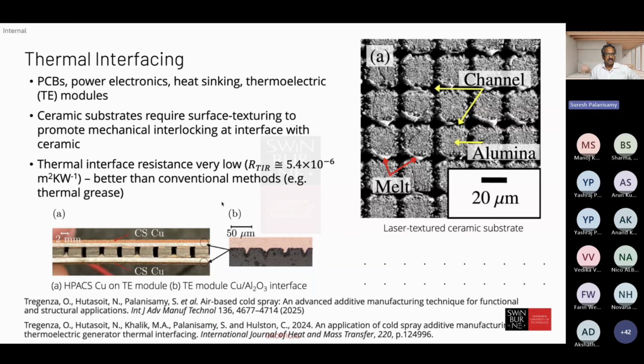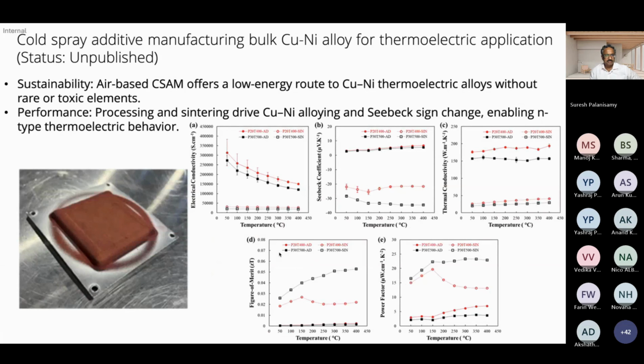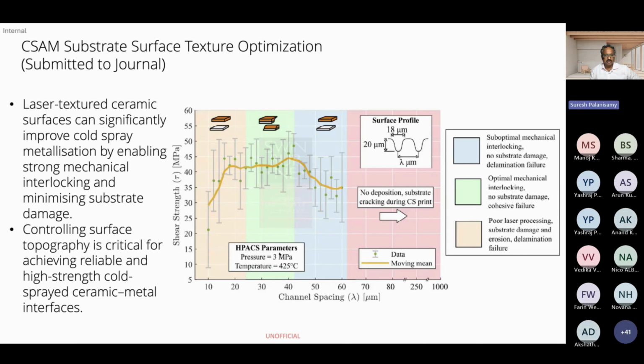So the thermal interface, as you can see here, is where the substrate changes. You can see how the particle bonding is happening with the surface substrate changes. You can see how much the copper particle has gone in between the grooves and how much bonding has happened. This is work which was extensively studied for a number of years. A few more of these copper nickel thermoelectric materials are shown, and this is currently in the process of publication. I spoke about this earlier also.